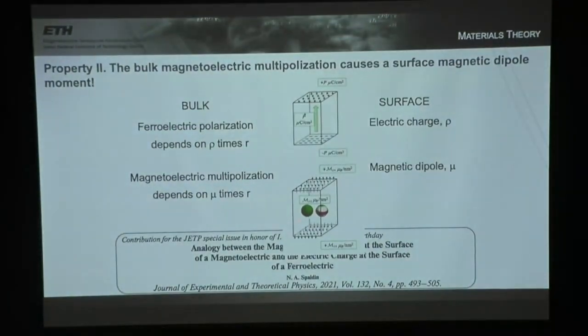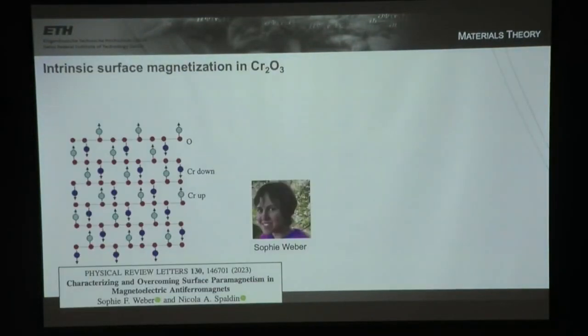Here I'm saying I want to have a magnetic dipole on the surface. I want a surface magnetization, and that I get from the quantity that's mu times R, and that's my magnetoelectric multipolarization. So there's a simple hand-waving argument. One can be, of course, a bit more rigorous. This was my COVID lockdown project. I actually wrote a paper on my own that had science content in it, which when you get to be our age, it's not so often that one gets to do that. So here in Cr2O3, for example, I have this MZZ component will give me a surface magnetic dipole equal to the size of the bulk magnetoelectric multipolarization.